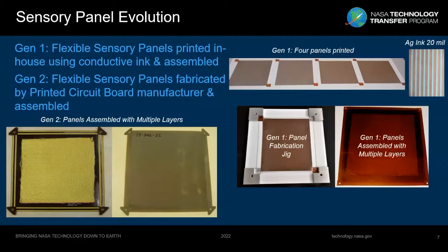And in order to assemble these, we had to have a special jig, and that's what you see in one of the images below, the Gen 1 panel fabrication jig. And then to the right is the 4-layered panel that's assembled. Due to the complexity of printing these panels and the fact that it's very hard for an inkjet printer to print a continuous straight line across a long distance, we went with an outside vendor to start fabricating and producing these boards, and we were able to actually have an outside vendor produce us these flexible printed sensory panels, and that's what you see in the Gen 2 panels.